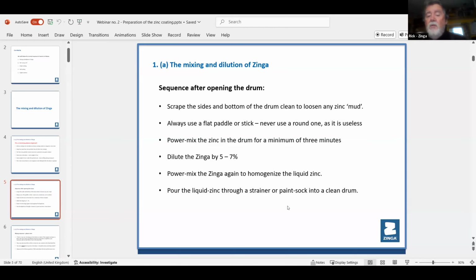Normally for brushing or spraying, we say you dilute by 5 to 7%. For example, if you have a 5 kilo tin, you'd put in 1 coffee cup, about 5%, a coffee cup of solvent. Very easy to mix inside then. You power mix for a few minutes, then pour it through a strainer, and then you can spray it. It'll come out smooth as glass.